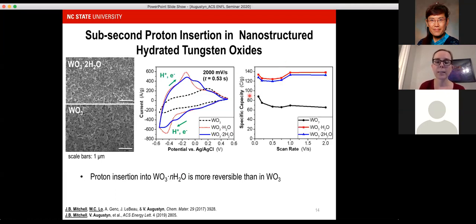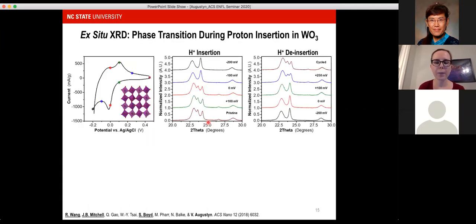And so here's that capacity, the area that's essentially in the curves, showing much higher specific capacity for the hydrated samples than the anhydrous sample, even though theoretically the anhydrous oxide, because it doesn't contain water, should have the higher specific capacity. At slow enough rates, this anhydrous tungsten oxide does have a higher specific capacity. So we see a kinetic difference, and it's stemming not from a surface area effect, but from the structural differences in the materials.